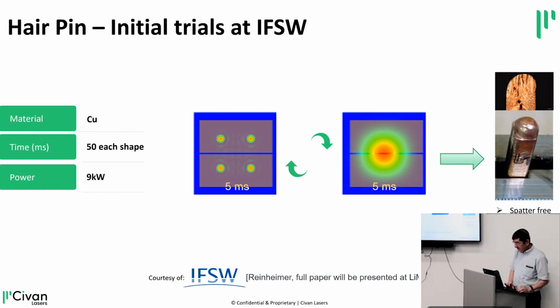We have a beam shape. This is a sequence of two beam shapes. For 5 milliseconds, we have a beam shape of these 4 points that just hits. This is the top view of the hairpins. So it just hits the hairpins over here. In 5 milliseconds, it melts it, so they collapse into one another. And then we have this beam shape for another 5 milliseconds just to stabilize the whole melt pool and re-solidify